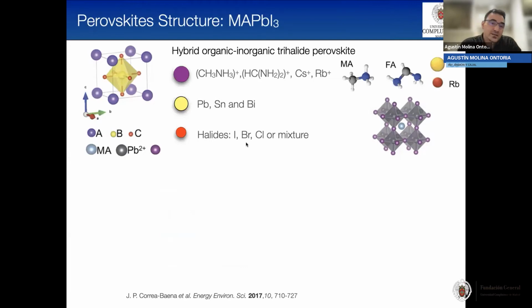So there is a large class of perovskites with promising photovoltaic characteristics, but out of those, methylammonium lead iodide was the first one made for photovoltaic devices. From the structure, we can see that we have the B cation, that is typically lead, tin, or bismuth, surrounded by halides in an octahedra. And then we have small organic cations such as methylammonium, formamidinium, or even cesium or rubidium that are filling the void between these octahedra.